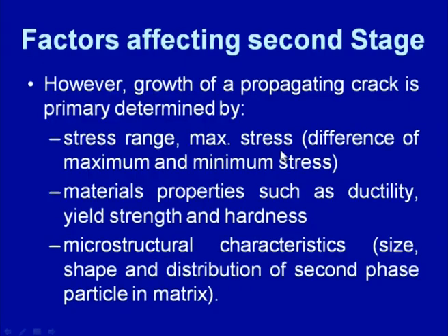To reduce the crack growth rate, or to delay the crack growth stage, it is necessary that ductility is high, yield strength is low, and material hardness is low. At the same time, stress range is also low, and the maximum stresses are on the lower side, especially when the load is of the tensile type.